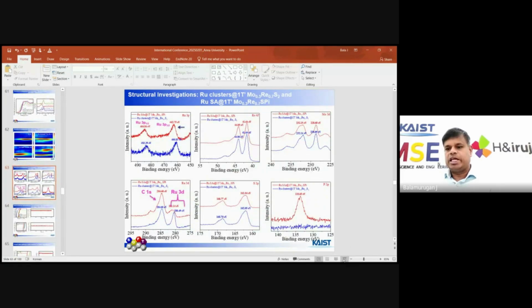And we also did the XPS analysis. From the XPS analysis, we also see the difference in oxidation states. Higher binding energy means a higher oxidation state. Lower binding energy means a lower oxidation state, maybe around 1 or 0. Yes. So the cluster may have a lower oxidation state, but in the case of the single atom, a higher binding energy. And we also did the other elements like rhenium, molybdenum, sulfur, and phosphorus, before phosphorization and after phosphorization.